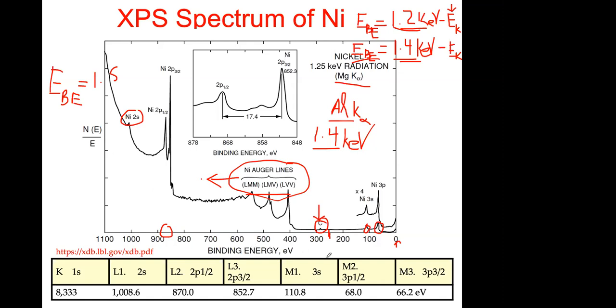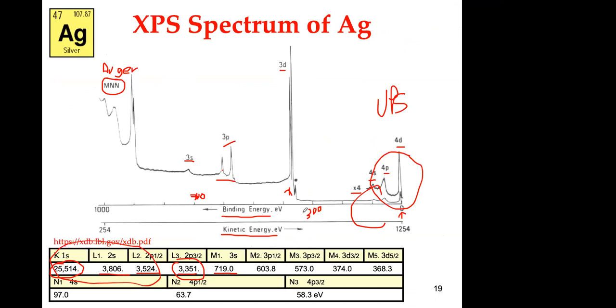If you plot this versus kinetic energy, which peaks are going to change? We have it versus binding energy, but you can plot it against kinetic energy. So in this case, you do it with a magnesium source, and then with an aluminum source. Aluminum is 1.4 kilo electron volts and magnesium is 1.2 kilo electron volts. What will happen?